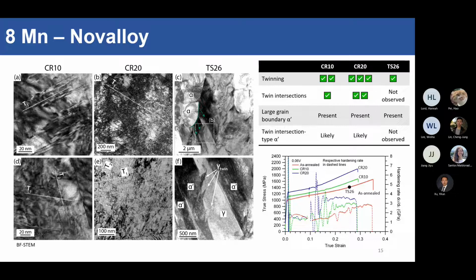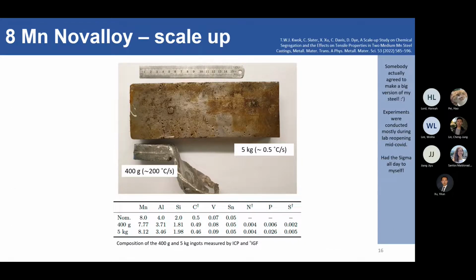So at the end of the day, we have more martensite in the cold roll samples because we allowed it to happen. We've provided it with a mechanism to form. And that's why we see the higher strain hardening rate here as well, and also higher UTS at the end of the day because you've got more martensite. So that's good. To summarize this, we can say that cold rolling first consumes the TWIP effect to actually enhance the TRIP effect later. So that's great. So now we moved on.